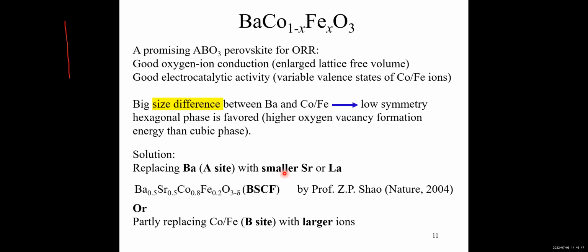So in our group, we have developed a series of perovskite materials for possible use as SOFC cathode. I just want to use 1 or 2 materials as an example to illustrate what we have done. This BCF perovskite oxide is quite promising as SOFC cathode because this material shows good oxygen ion conduction due to the enlarged lattice free volume, and the activity is also very good due to the variable valence states of cobalt and iron.